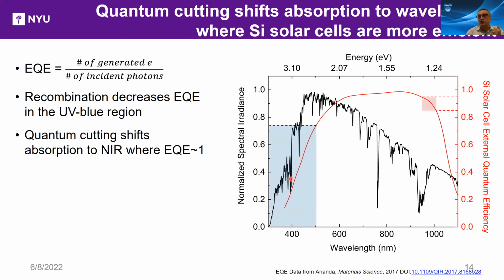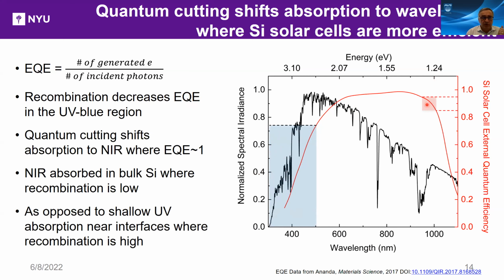So taking all these photons and putting them over here also puts them in a place where the EQE is closer to 100%, or 1. That's because the near infrared goes deep into the silicon, absorbing in the bulk where the recombination is low, whereas UV is absorbed shallow near interfaces where the recombination is high. So there is more than one way to win.